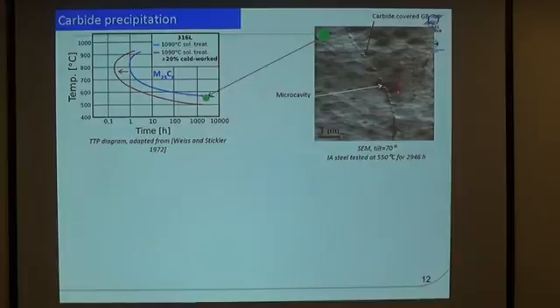And now I come to conclusions. For the first time intergranular damage has been found in 316 L type steels. We need high carbon content to nucleate these voids which is a bad thing obviously for usage of this material and high nitrogen should only be added if carbon is low. The effect of phosphorus was less than expected. The most detrimental temperature was between 550 and 600 degrees. Sigma 1 was identified as a threshold to have a threshold to nucleate this and we propose to use in post-processing a relationship based on sigma 1 to predict the damage development. Thank you very much.